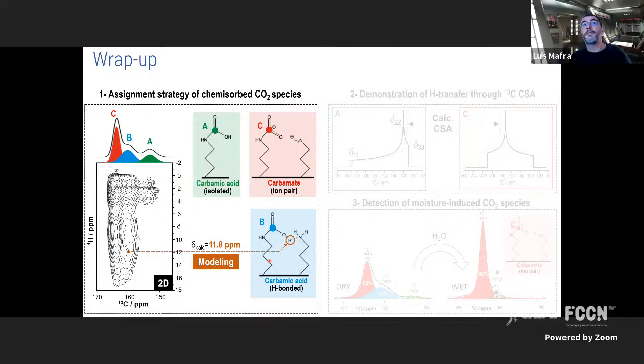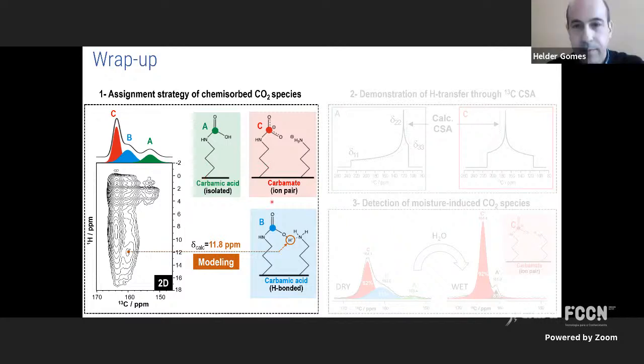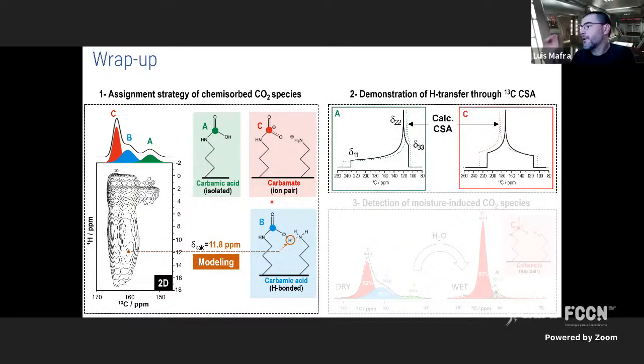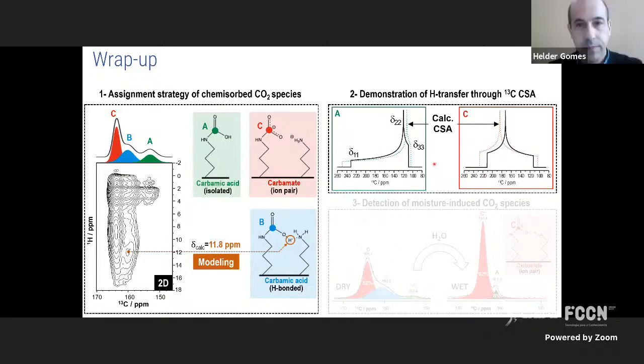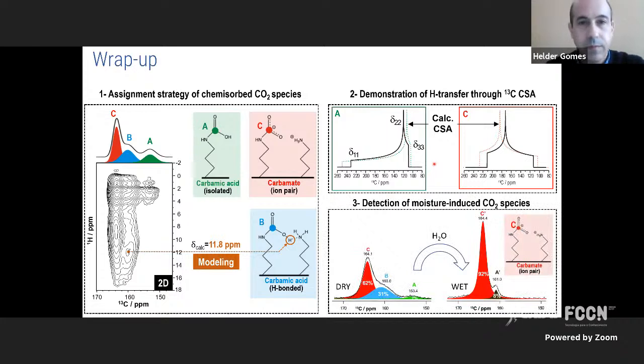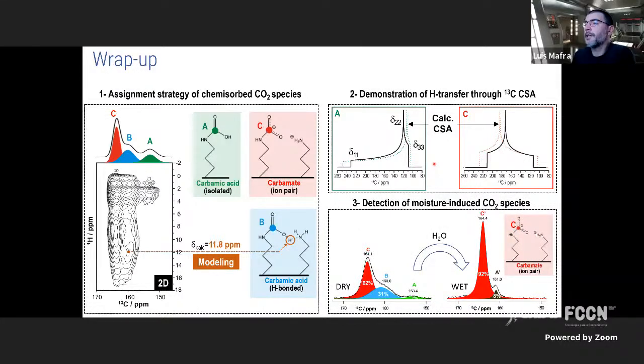So just to wrap up, this is the last slide. I showed you that with two-dimensional experiments, we can have a better assignment of these surface species. We can couple these with calculations and at least assign 3 different chemisorbed species. We can use chemical shift anisotropy to demonstrate proton transfer in our surfaces. And we can also monitor and identify moisture-induced CO2 species. So with this, I will probably postpone the future prospects, but I will go immediately to the last slide.